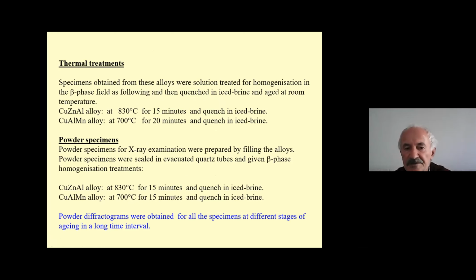Specimens obtained from these alloys were solution treated for homogenization in the beta phase field as follows, then quenched in ice brine and aged at room temperature. These temperatures were selected in the beta phase regime of the material. These are 830 and 700 degrees for the copper-zinc-aluminum and copper-aluminum-manganese alloys, and homogenization times were selected as 15 and 20 minutes for the copper-zinc-aluminum and copper-aluminum-manganese alloy samples.